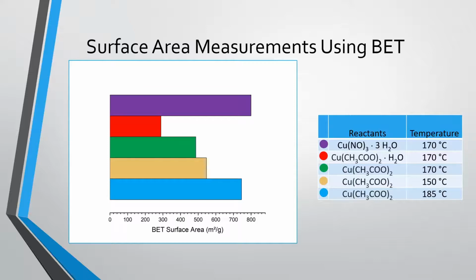Copper BTC from copper nitrate and copper BTC at 185 degrees seem to have the largest surface areas, where the rest of them were around the same, or in the case of our copper acetate monohydrate sample, significantly lower.